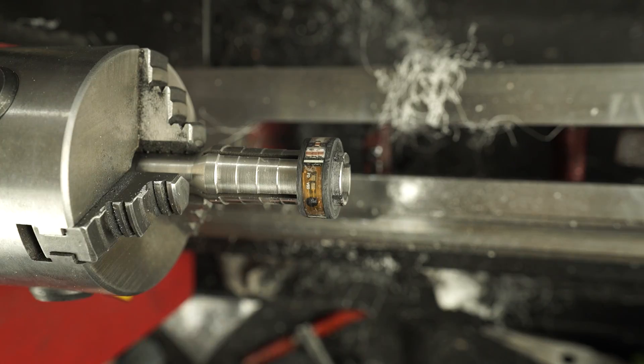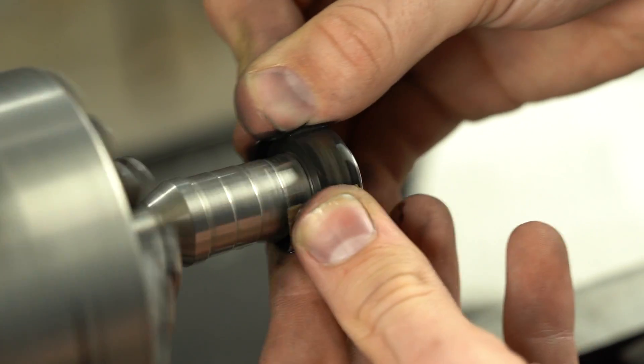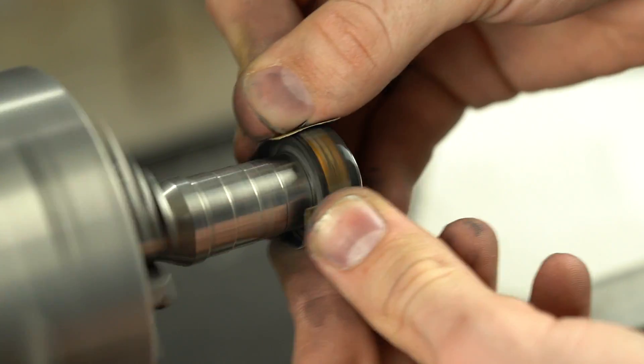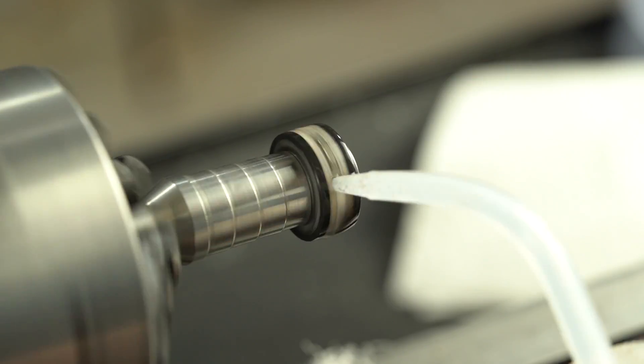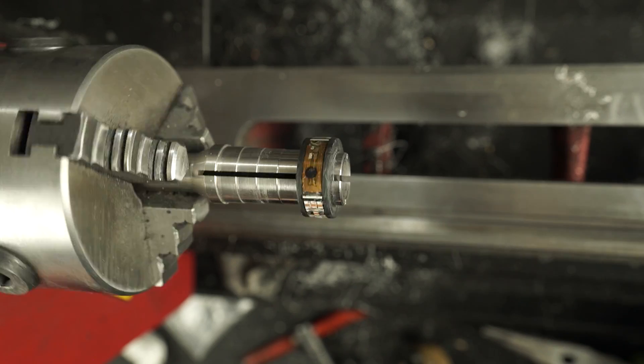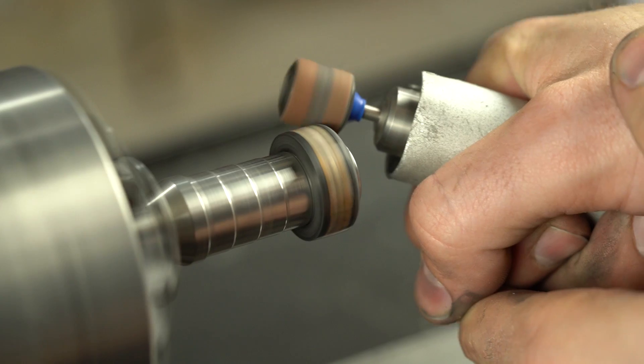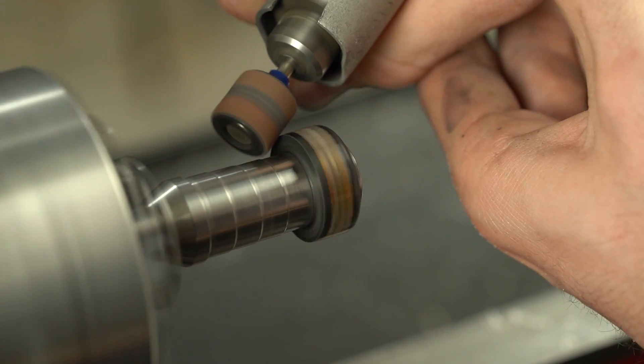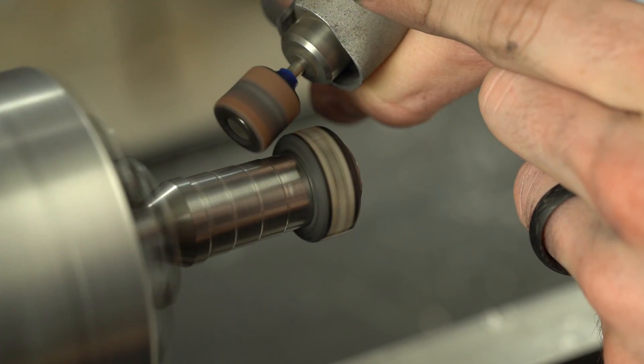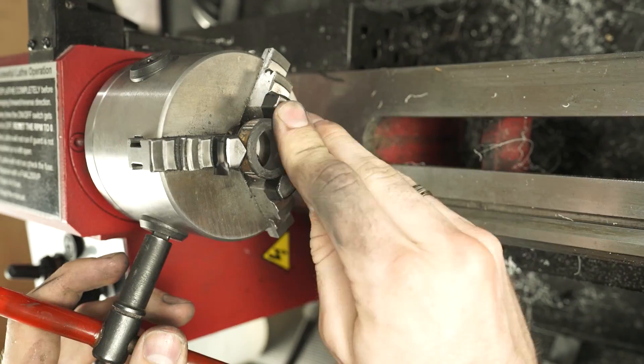As a finishing touch, I wanted to add bevels to the ring. This is a challenge with carbon fiber because it's such a soft material. If I were to use my lathe bit to do this, it would leave a nice bevel and it would be even, but the edges of it would be rough. So I'd have to use sandpaper to get rid of that. And long story short, basically that would round out those bevels and not make them look as good. So you want to do as few steps as possible. So I'm basically going to be skipping straight to a really high grit sandpaper. And I'm going to be using the Dremel to put those bevels into place. So I'm holding it as carefully as I can at a 45 degree angle, and I'm carefully just adding those bevels to it. And because the sandpaper is so smooth, it leaves us with an acceptable surface finish that all I need to do now is use a buffing wheel at the end. And that will polish it up, and that way we won't have any of those sanding marks left in it. And we'll still have those nice crisp bevels that we were going for.